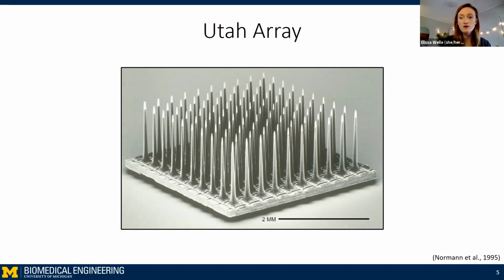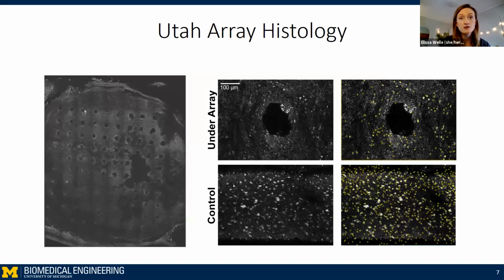However, it's fairly well known that conventional silicon electrodes in the brain cause scarring. And our lab was given a rare opportunity to do histology on a single non-human primate implanted with a Utah array for roughly 2 years. And while this data is very preliminary, we can obviously see scarring caused by the Utah array. This is just one slice along the shank, not necessarily at the tip of the shank where the electrodes are. What we're seeing here is endemic throughout.